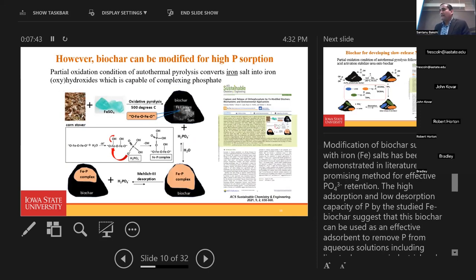However, biochar can be modified for high phosphorus absorption. Partial oxidation condition of autothermal pyrolysis converts iron salt into iron oxyhydroxides, which is capable of complexing phosphate. Here I've shown the graphical abstract of this published paper.